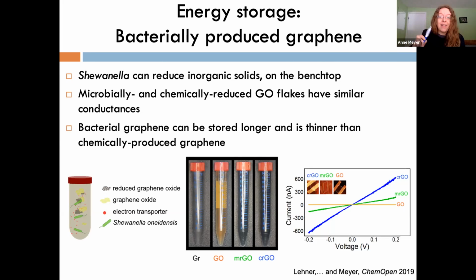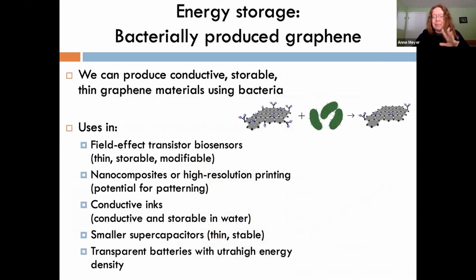And we also have distinct advantages over the chemical approach, which is that our bacterially produced graphene can be stored longer than the chemically produced graphene. So after 2 weeks, the chemically produced graphene is clumping together, which makes it less thin, less conductive. But ours, we don't see clumping after 2 weeks. Now ours is also thinner, which means that it's more flexible as well. So yeah, I think it's pretty exciting that we're able to produce graphene materials using only bacteria and some graphite. And there's lots of interesting applications for this in the future, potentially, right?